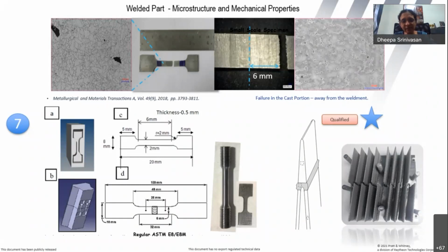But I will definitely tell you that for each of the case studies, including this page that I'm showing you right now, including the build plate on the right hand corner for this particular geometrical part, we defined and redefined, and we had a benchmark. What was my benchmark? I don't have it with cobalt chrome moly, because cobalt chrome moly is not an aero section, a gas turbine or an aero engine part in that sense. But my nearest equivalent is cast FSX 414. So when I'm implementing this in a case study like this, I took this as my reference, and I said my additive part has to be better than this.